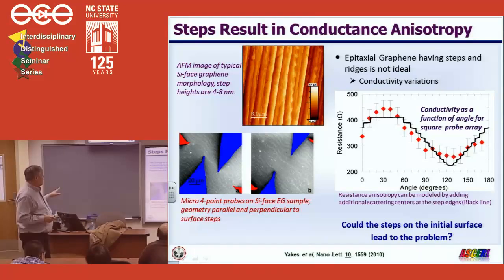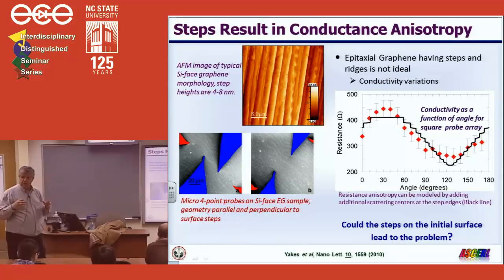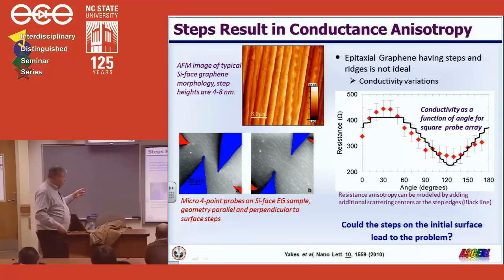So just to remind you, we have the terrace and step morphology. That's the same picture I showed you earlier. Michael Yakes and co-workers used STM microprobes, and they determined that there was a conductance anisotropy associated with the steps. So the steps added resistance. And this is actually well known. Yuming Lin recently published on some of the IBM FETs that the best FETs were always on a terrace. FETs that straddled the step had poor properties. And so it is now well established that you would like to make your high quality FETs on a terrace or a large flat area of graphene.